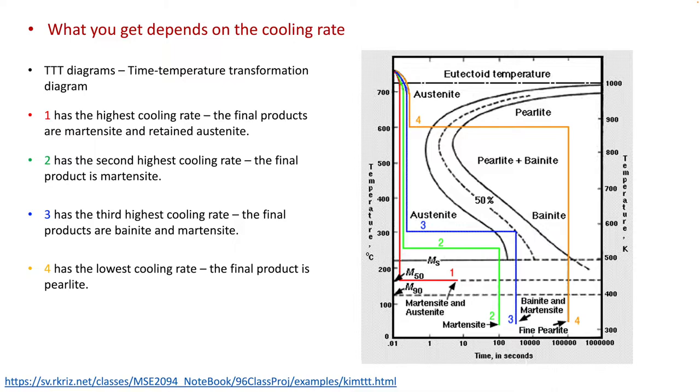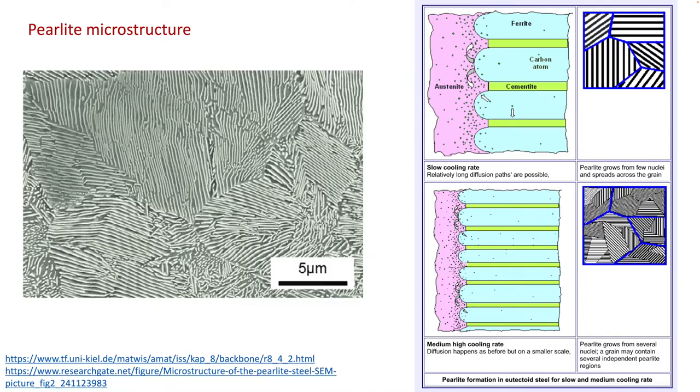Just by looking at the figure on the right, you can see a trend here. If the cooling rate is very high, the steel can easily turn into martensite. If the cooling rate is intermediate, then the microstructure is something we call bainite. You will see what bainite is very soon. At low cooling rate, the final microstructure is pearlite, which is the phase we have in the phase diagram. Therefore, phase diagram can only capture the phases from slow cooling at equilibrium.